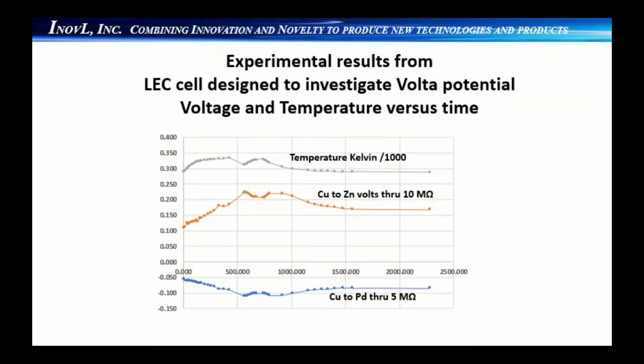This slide shows a plot of the voltage produced at various temperatures over time, from the glass cell shown on the previous slide. You can see that as the temperature increased, the absolute value of the voltage between the copper to zinc fins and between the copper fin to the working electrode increased.